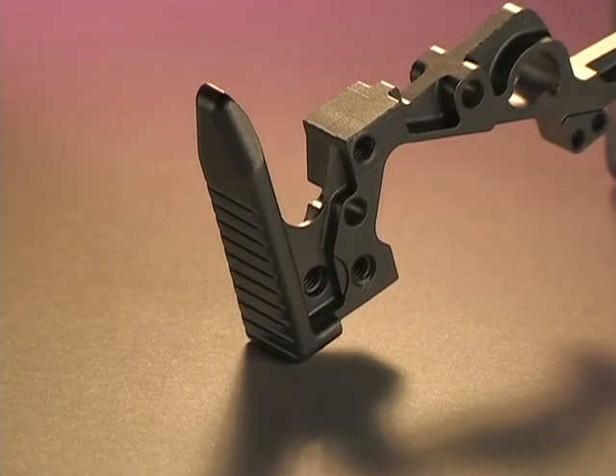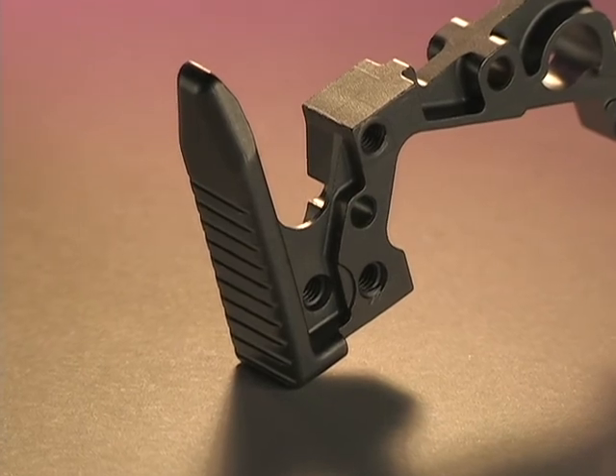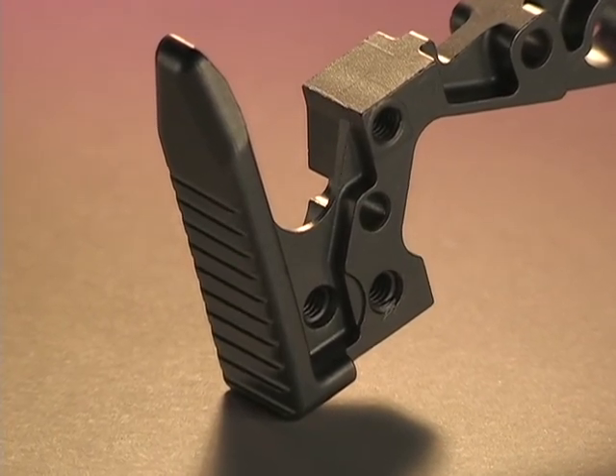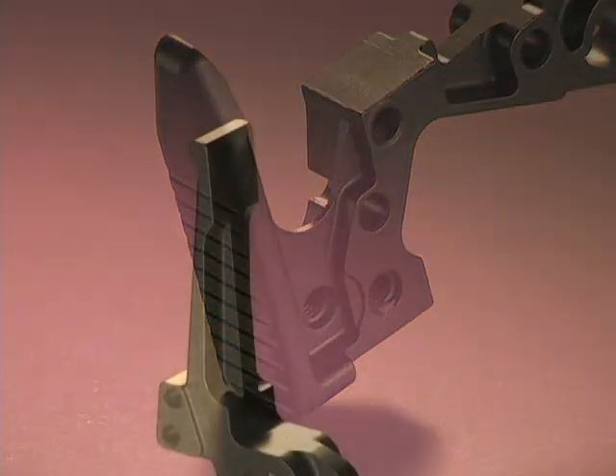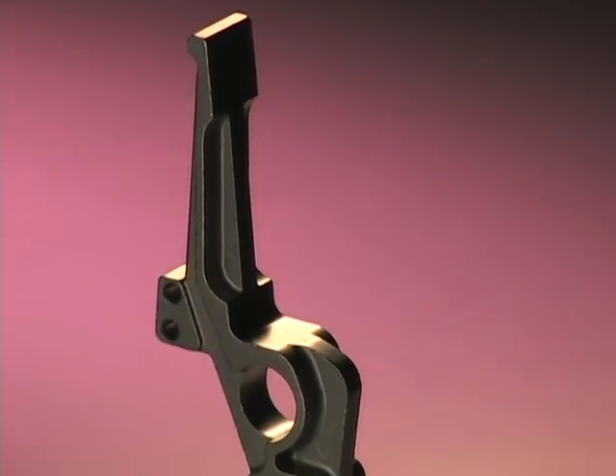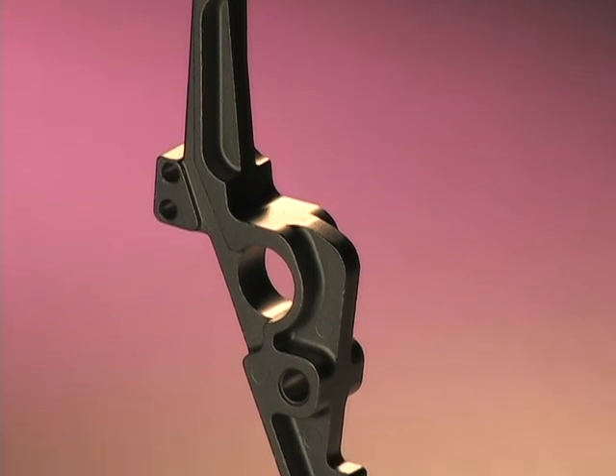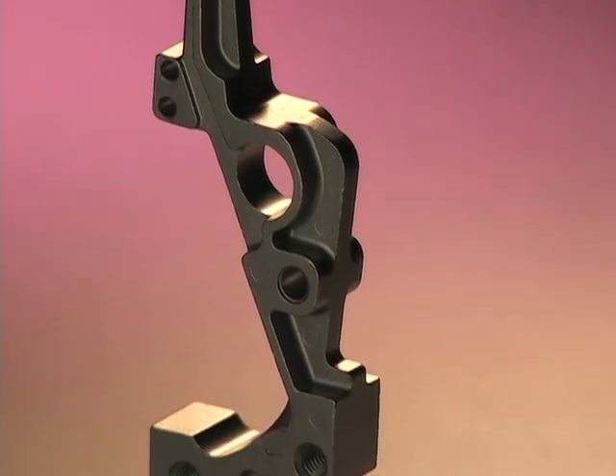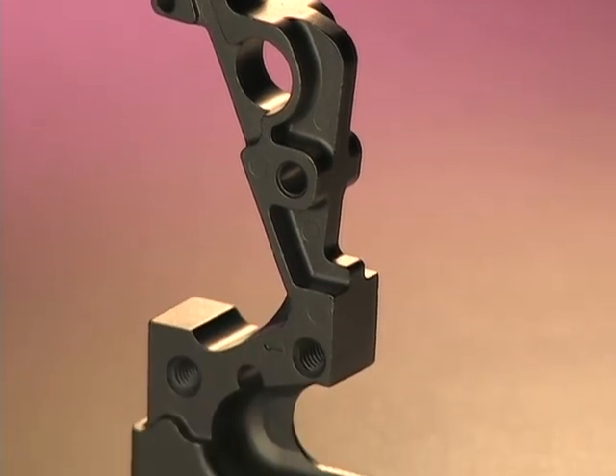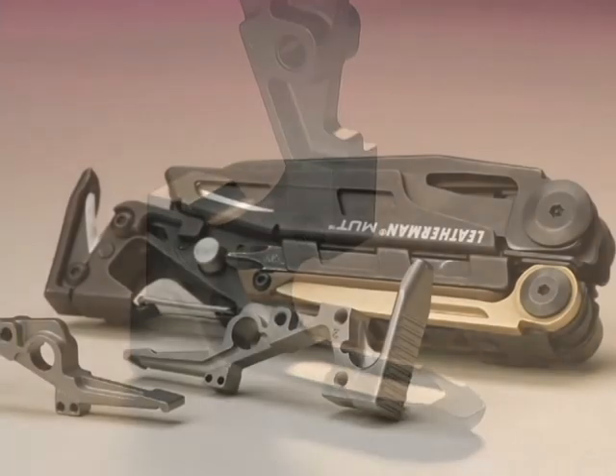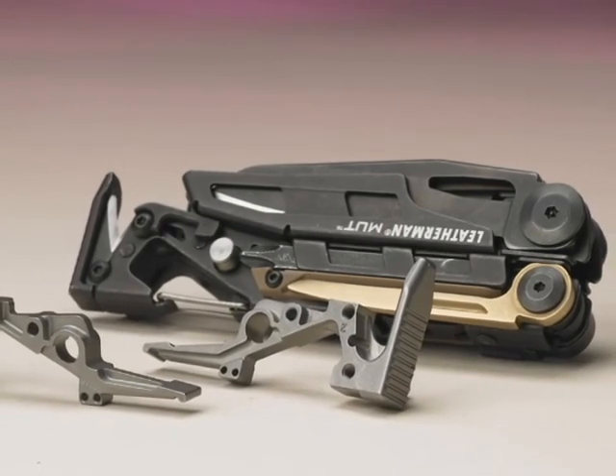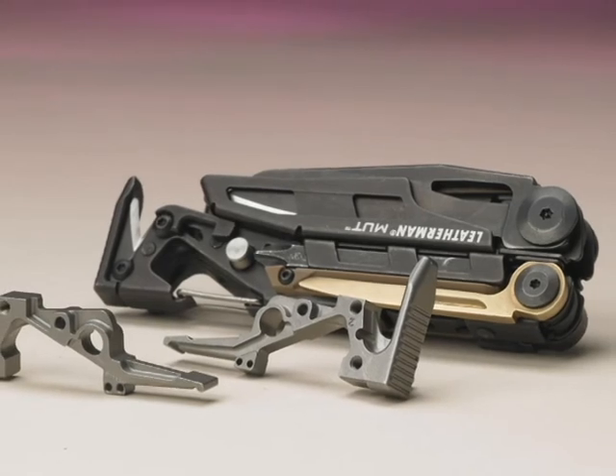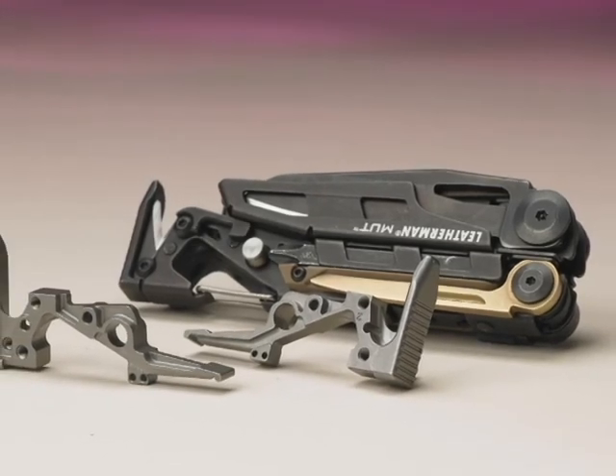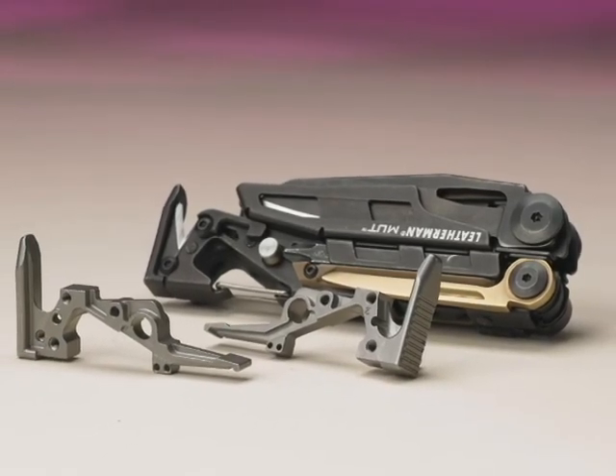It is formed to a density of 7.5 grams per cubic centimeter and has an ultimate tensile strength of 175,000 psi, yield strength of 158,000 psi, heat-treated 35 to 40 HRC hardness, and a minimum 6% elongation. Secondary operations include threading 2 tapped holes, age hardening, and glass bead blasting, and an optional blackening treatment performed by Leatherman.